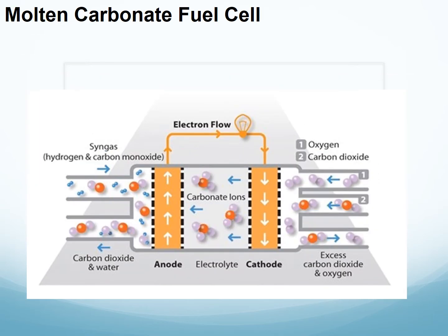Molten carbonate fuel cells are currently being developed for natural gas and coal-based power plants and are used for electrical utility, industrial, and military applications. These fuel cells run at a very high temperature, around 650 degrees Celsius, and the electrolyte is composed of a molten carbonate salt mixture suspended in a porous, chemically inert ceramic lithium aluminum oxide matrix. When coupled with a turbine, molten carbonate fuel cells can reach an efficiency of about 65%, but when used with cogeneration, the efficiency can be up to 85%.